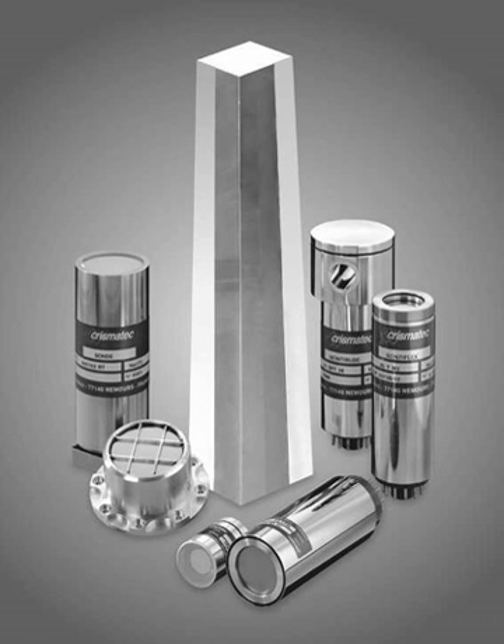The fast scintillation light is emitted in the UV band, 220 nanometers, and has a 0.7 nanosecond decay time, smallest decay time for any scintillator, while the slow scintillation light is emitted at longer wavelengths, 310 nanometers, and has a 630 nanosecond decay time. It is used for fast timing applications, as well as applications for which pulse shape discrimination is needed. The light yield of barium fluoride is about 12 photons/keV. Barium fluoride is not hygroscopic.